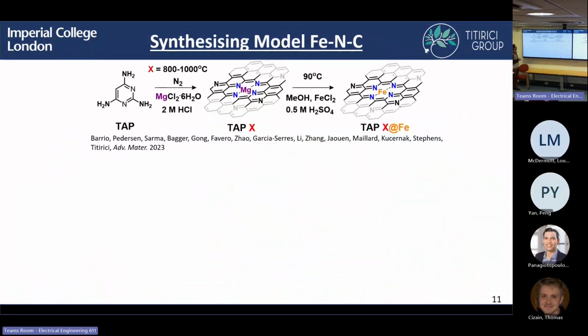And so what we did is we took this precursor called triaminopyrimidine, or TAP for short. So this looks just like melamine, but with 1 less nitrogen, and doesn't just go straight into evaporating. Instead, it forms a liquid before evaporating at high temperatures. So you end up with this liquid phase reaction during the pyrolysis. And so what we did is we mixed this with our magnesium chloride hexahydrate, which is our hard template and active site template. And we pyrolyzed this between 800 to 1000 degrees for 1 hour, wash this in acid. We end up with this material called TAP, X denoting the pyrolysis temperature.